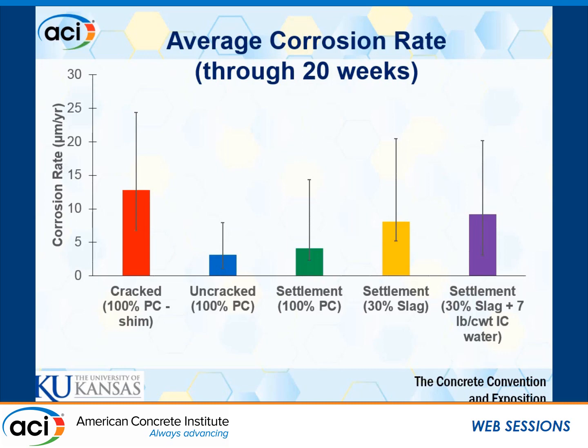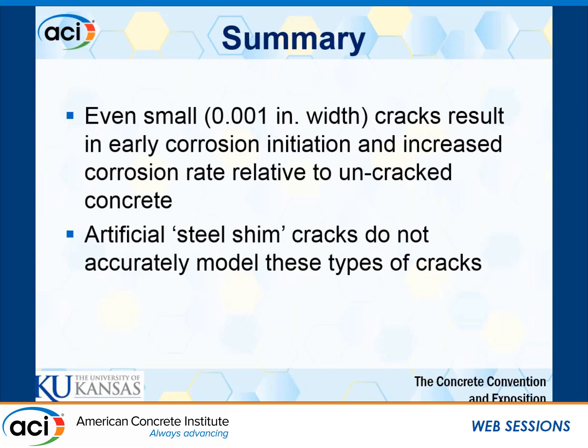And our lowest one, of course, is going to be with our uncracked condition. And only slightly higher than that is the settlement cracking specimens with 100% Portland cement. And kind of like how we saw early initiation with slag, with or without internal curing, the average rates for those were about double that of just 100% Portland cement alone. More on that in a minute.